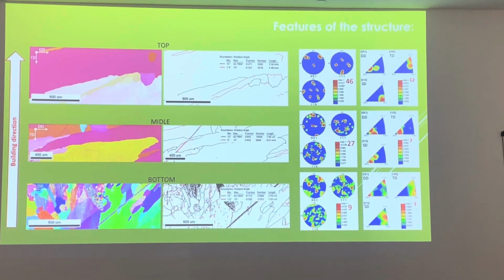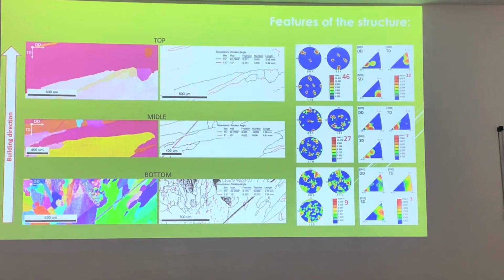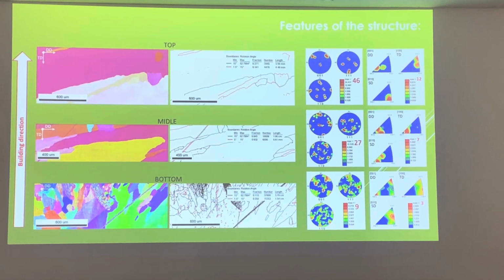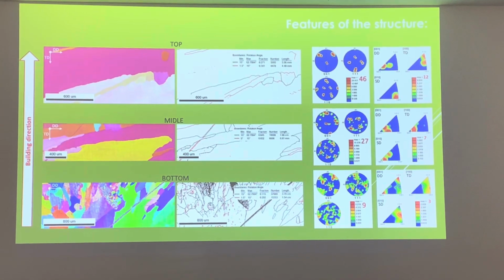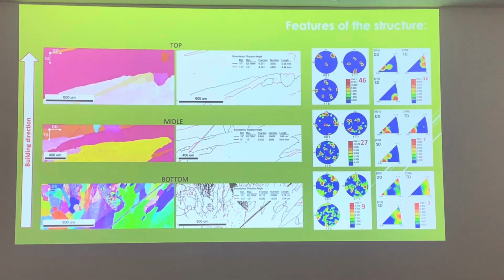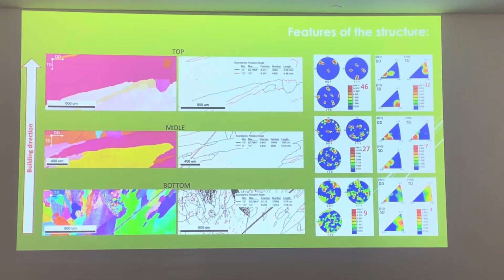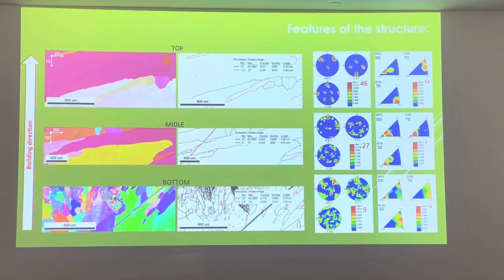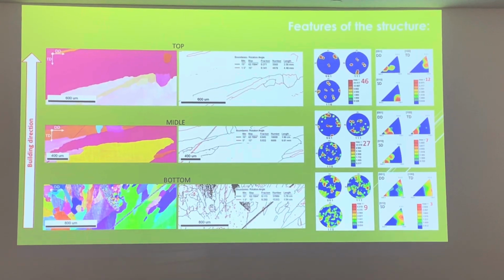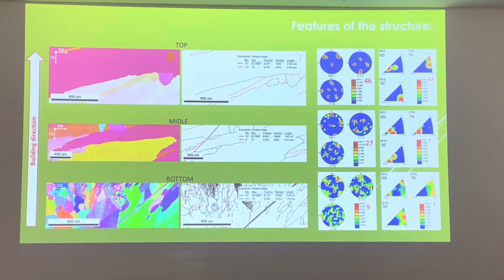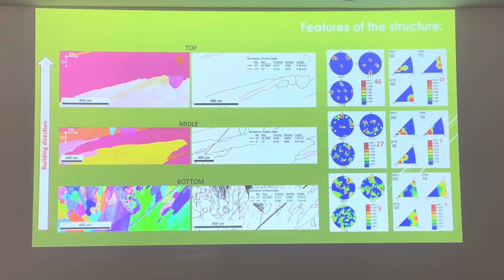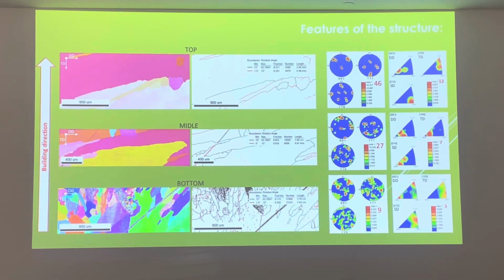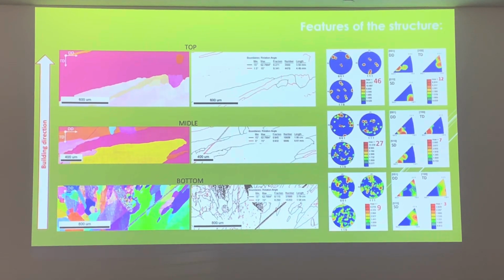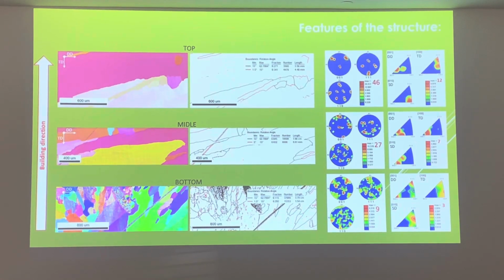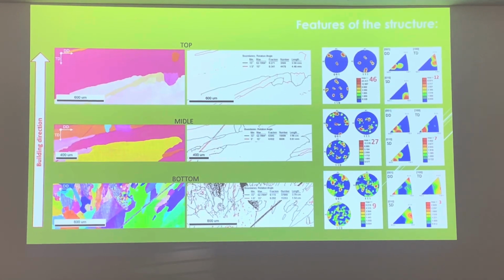And if we consider the middle part of the billet, we have steady state mode and relatively uniform distribution of grains. So if you want to print a bulk billet, you should cut the first 3 layers of deposition and the last 3 layers, and the billet will be solid and uniform with uniform mechanical properties.